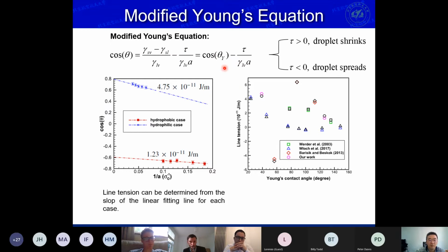So based on this modified Young's equation, we can do MD simulations. For instance, for the hydrophobic case and the hydrophilic case, we both simulate 5 different sizes of droplets. We measure the contact angle, and then we plot the data, the cosine of the contact angle against the curvature of the contact line. If we do linear fitting of the NEMD data, from the slope of the fitting line, we can determine the line tension. For these two cases, the magnitude of the line tension is on the order of 10 to the minus 11, and then we draw the data on this figure.